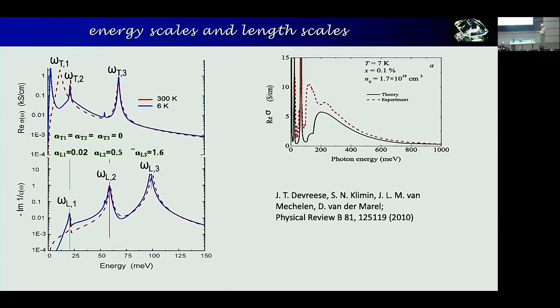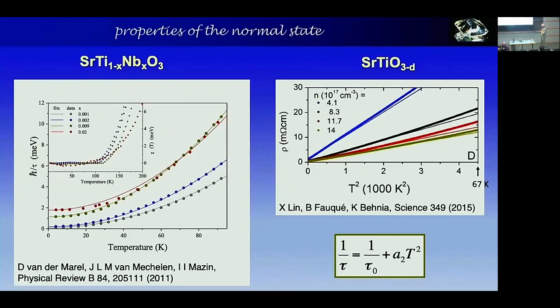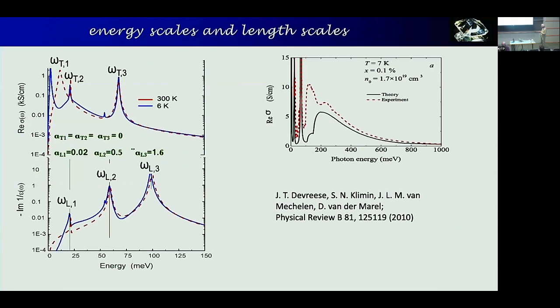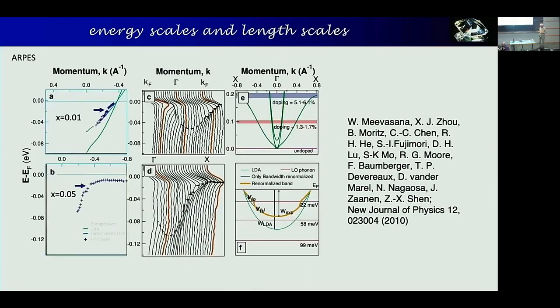So there's another thing you can also wonder: where does this factor of 2 in the mass come from? That is important for the story about energy scales, and that actually has to do with electron-phonon coupling. So the electrons couple to the longitudinal phonons. Those phonons have energies of more than 25 milli-electron volts. They do not couple to the transverse optical phonons, or very, very weakly at least. But if you just assume these couplings that you can actually calculate from the data also, you get a pretty good fit to the entire spectrum, including a mid-infrared band that I didn't mention before and won't mention anymore.